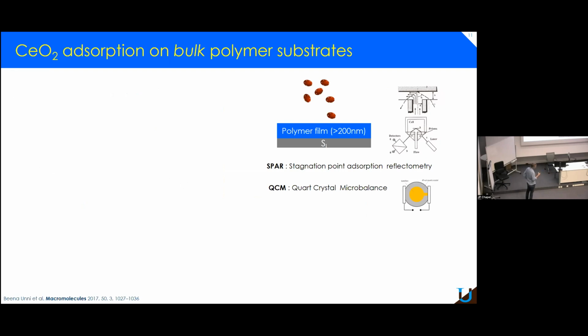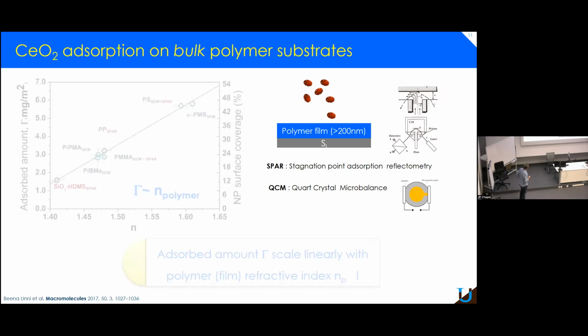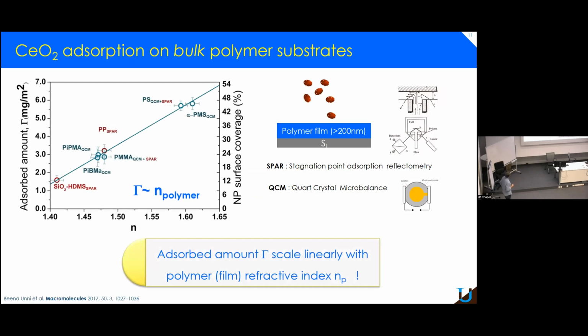And so we decided to check that and to adsorb the cerium oxide nanoparticles on bulk polymer films. Bulk meaning at least 200 nanometer polymer films, to see the variation of the adsorption as a function of the nature of the polymer and its refractive index. And strikingly, what we saw is that the adsorbed amount scales linearly with the refractive index of the polymer on which you are trying to adsorb the particles. We used two typical techniques to measure the adsorption: optical reflectometry using a stagnation point, and also QCM, a typical setup to measure adsorption accurately.